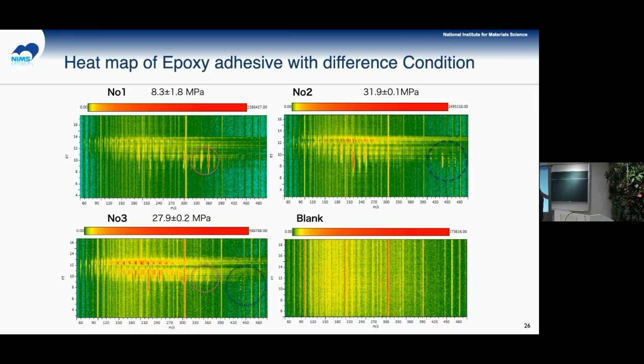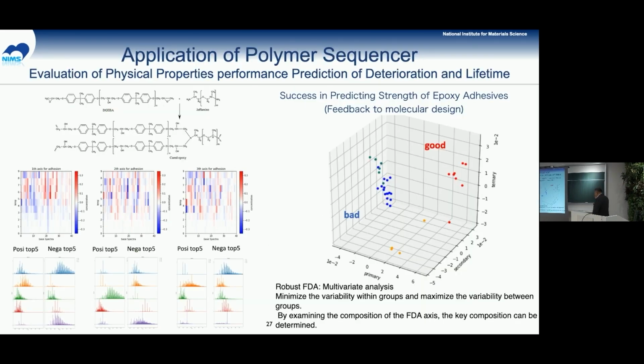By using these, we got the mass spectroscopy data. That's shown here, and there is some difference you can see. Of course, it's quite difficult to characterize these network structures, but by taking mass spectroscopy, somehow you can tell the difference of the adhesive chemical structures. Then by using our NMF analysis, we get these basis vectors, and we perform the multivariate analysis using them. As shown here, we can tell which mass spectrum shows good adhesive properties or bad adhesive properties. So we can tell after curing, after networking of the polymers.